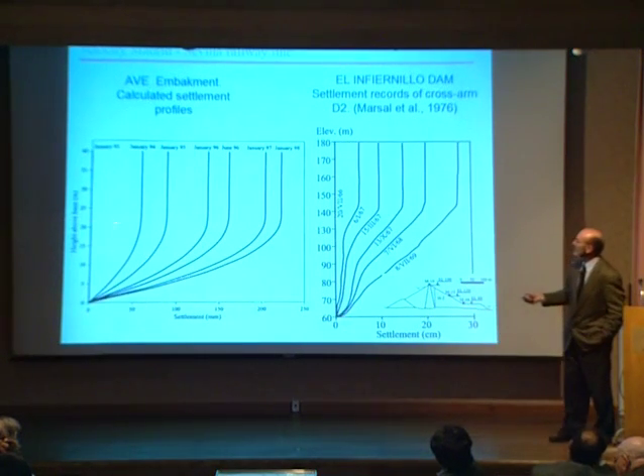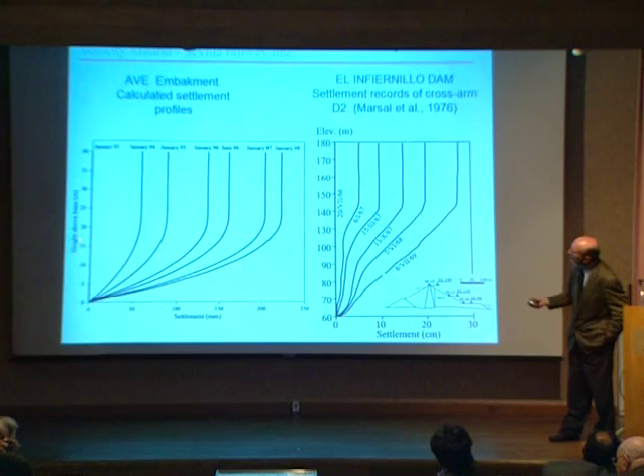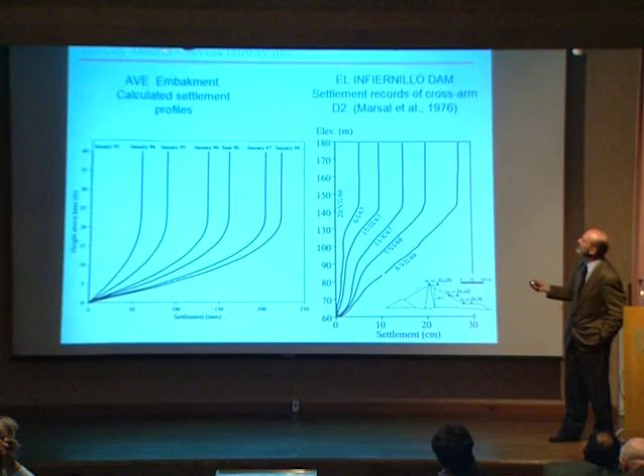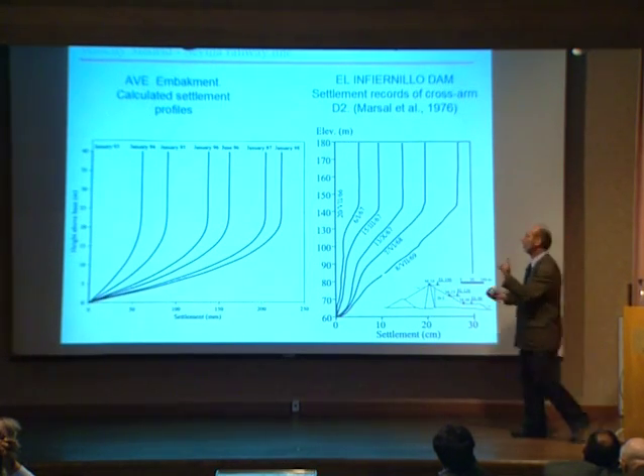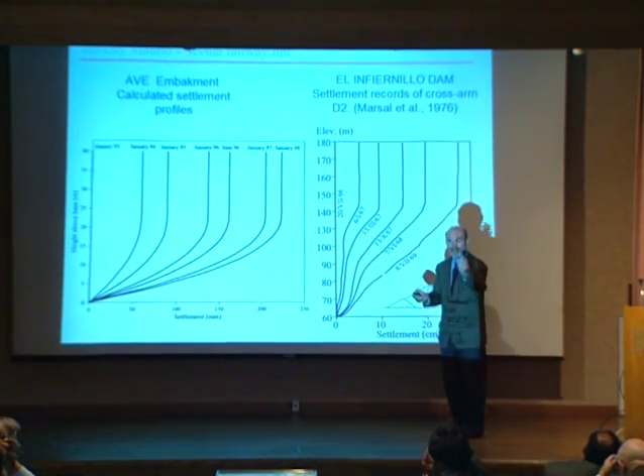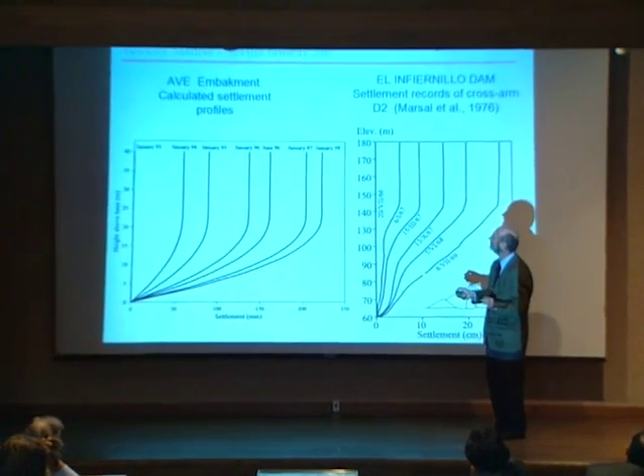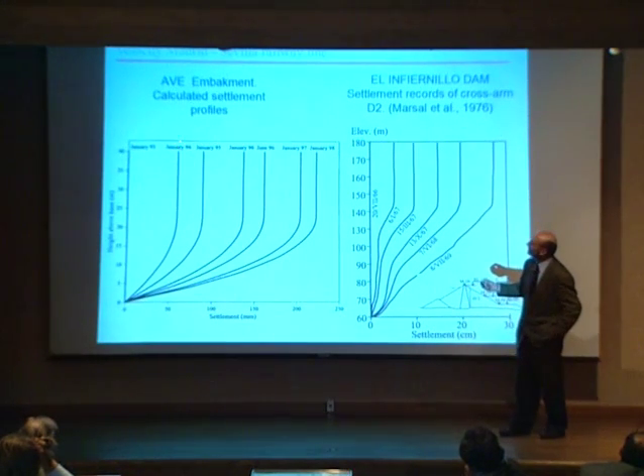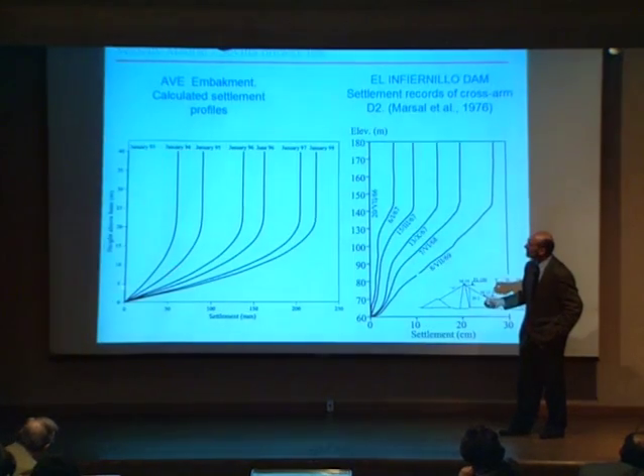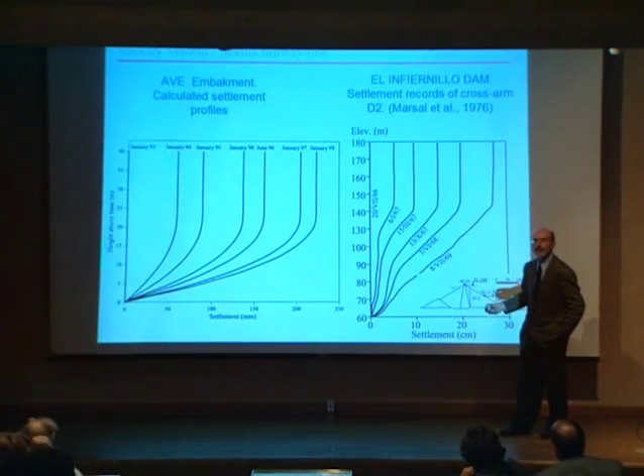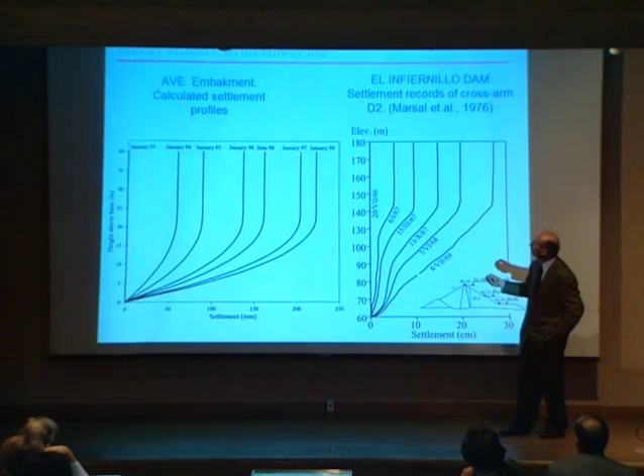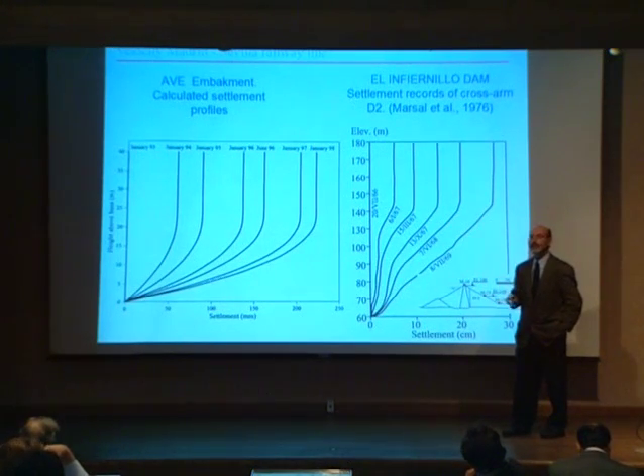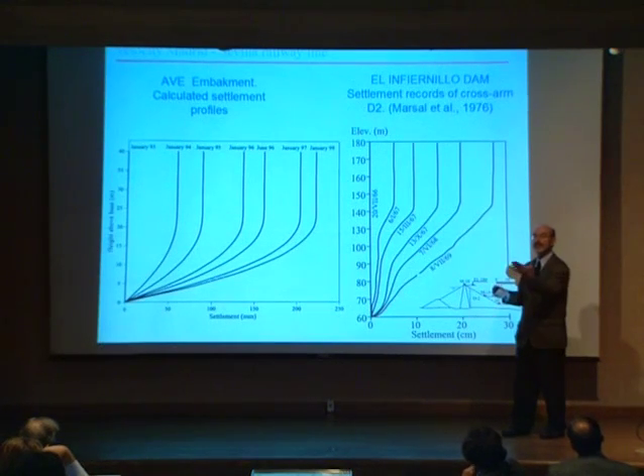This is the computed settlement for this embankment of the Sevilla-Madrid line. Of course, they didn't measure anything. I wish they had installed continuous extensometers along the embankment, but they didn't do it. But what we calculate is that in the upper part of the embankment, nothing happens, and then all the deformation is explained in the lower part of the embankment. And this is a different curve for different times. But this is what should be if there is a threshold sigma y value.